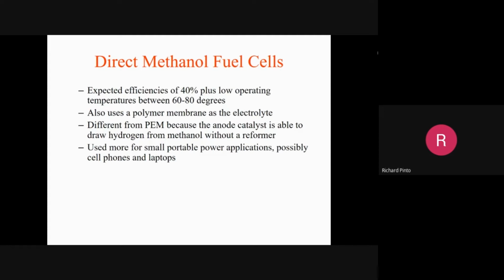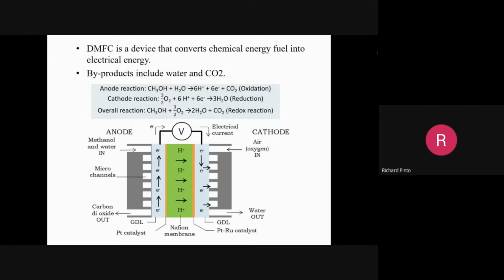So they have very limited applications because power generation is not very high, but they are safe because they use only methanol. But there's a drawback: power generation is not very high and they also give rise to carbon dioxide. In principle, and in reality, they are not clean energy sources. Now, the DMFC picture is shown here, which again shows the schematic very clearly. The byproducts include water and carbon dioxide, as shown here. And the reaction is shown above.